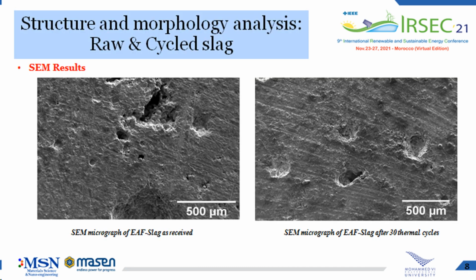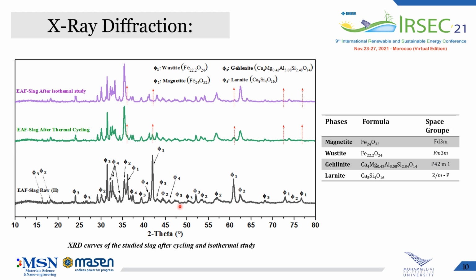The visual inspection is not enough, so we have prepared 2 different samples, one as received and the other after thermal cycling for the SEM analysis. No further cracking or morphologic modification were detected. The XRD analysis for the received slag shows 4 main phases, which are magnetite, wustite, gehlenite, and larnite. After thermal cycling or isothermal test, the wustite phase disappeared and the intensity of magnetite peak increases, which means that the wustite has oxidized and turned into magnetite, which made the material more thermally stable.